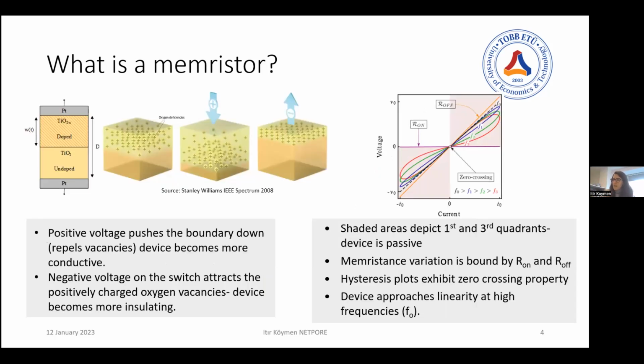So the first figure is dated on purpose, because it's a figure from when the first prototype of the memristor was reported by HP Labs, basically over 30 years after its postulation. They reported a titanium oxide device. The active layer is titanium oxide. Part of it is stoichiometric. The other part of it is doped.